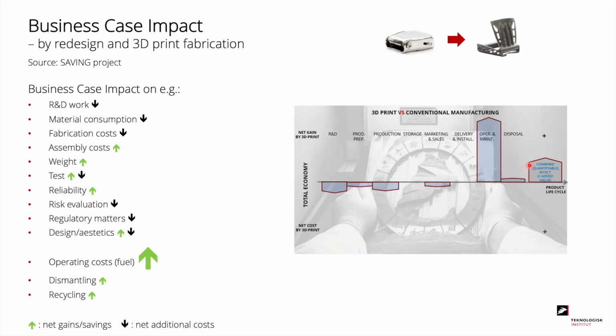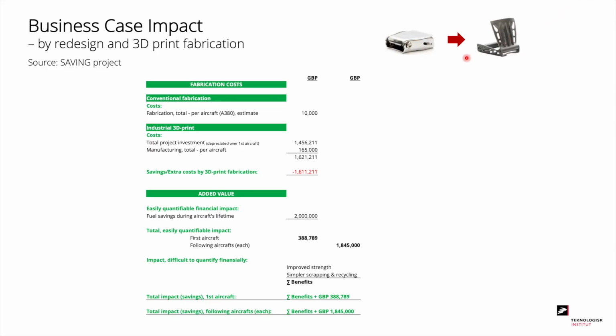indicating the big fuel save by this change to additive manufacturing. Putting figures on this, at the top we have the fabrication costs, and the conventional buckle sums up to about 10,000 British pounds for the full aircraft, and using additive manufacturing we first have to invest in the R&D work, which is quite costly, namely almost 1.5 million British pounds, and on top of that the fabrication cost or manufacturing cost for the titanium buckle is 165,000 British pounds, meaning almost 17 times higher than the traditional buckle, and together we get an extra cost for the first plane of 1.6 million British pounds.